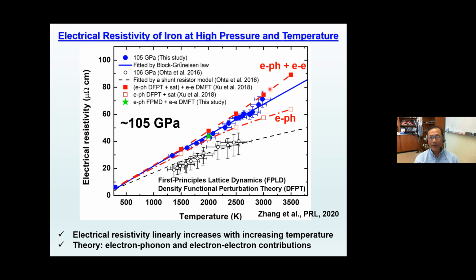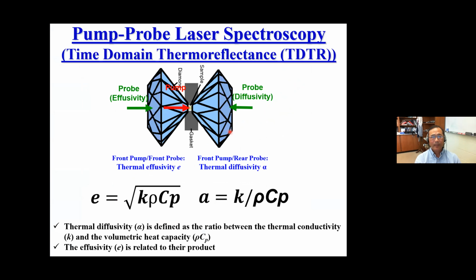We also did theoretical calculations. Ron Cohen and colleagues did the theoretical calculations in which they consider both electron-phonon contribution as well as electron-electron contributions. So it looks like at higher temperatures, the electron-electron contributions become more dominant and account for about 20% of the conductivity or resistivity. But at relatively low temperatures, electron-phonon scattering is the most dominant mechanism.